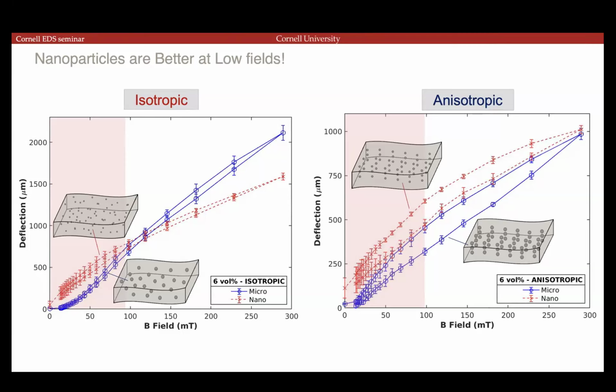So once the field magnetizes the particles, then they'll move towards the field. But then if you apply an orthogonal field, it's still very random in orientation. And so if the field is strong enough for them to magnetize, they'll magnetize along the field. And then now there's no reason for it to torque. The magnetization is parallel to the magnetic field.